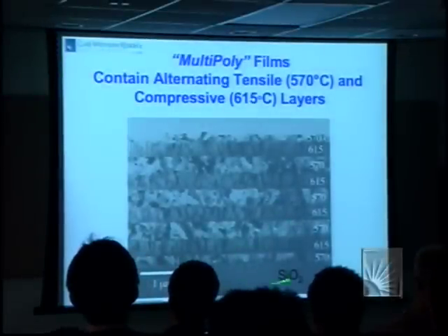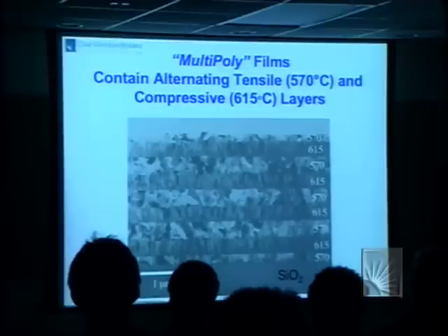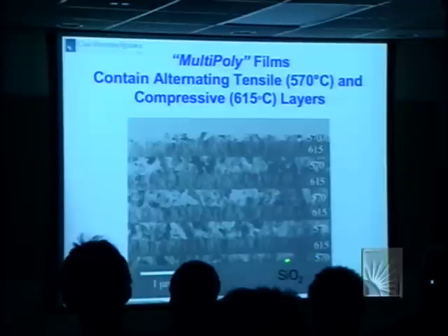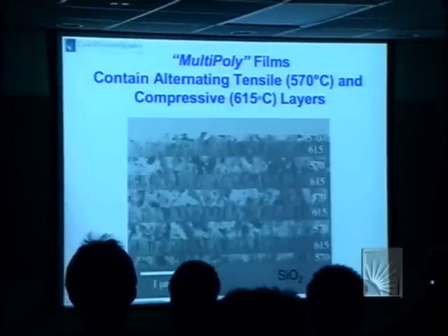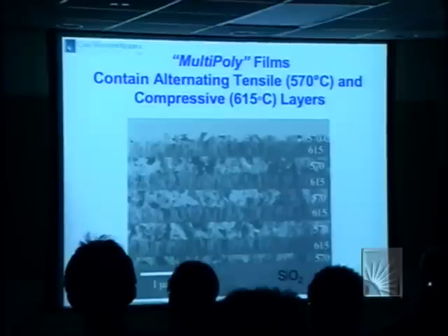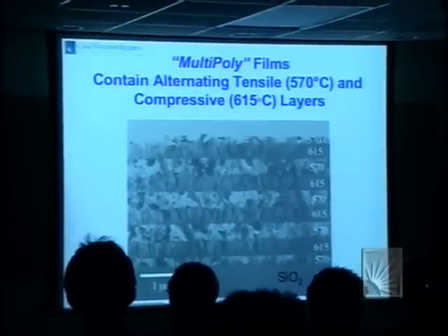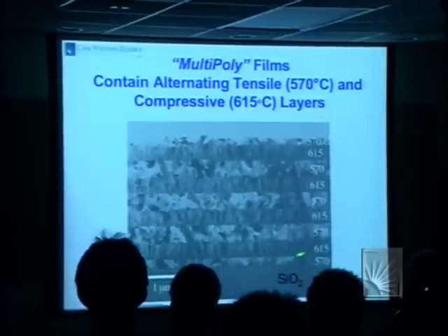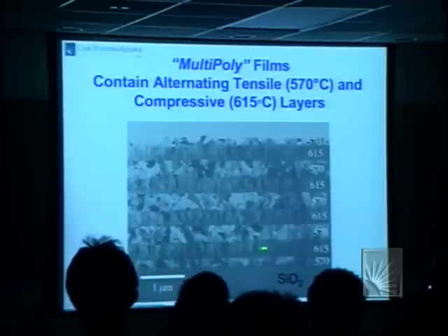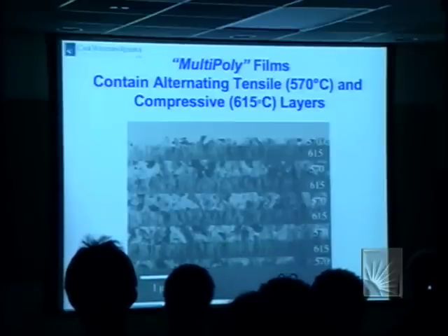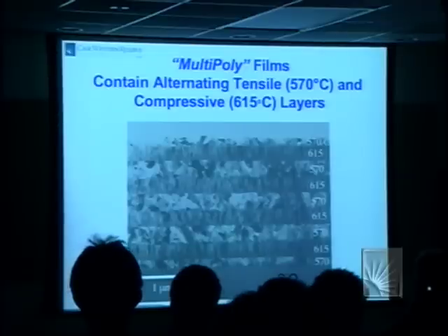So here is the SiO2 sacrificial oxide in which we build the structure. And in this experiment, we deposited a thin layer, about 1/2 micron, at 570. And at this thickness, it remained amorphous during that brief heat deposition time. We then raised the temperature and went to 615. During the 615 deposition, the material at 570 crystallized. Okay, so far? And now a miracle happened.